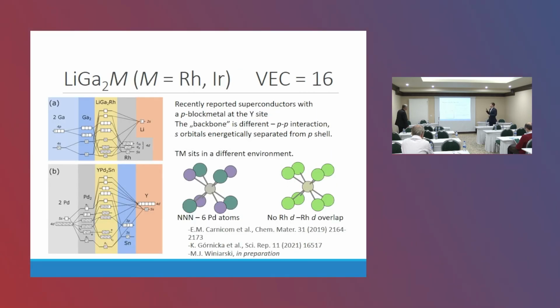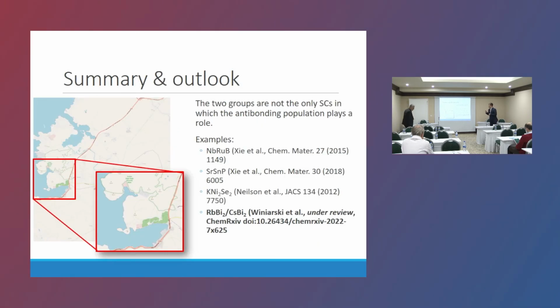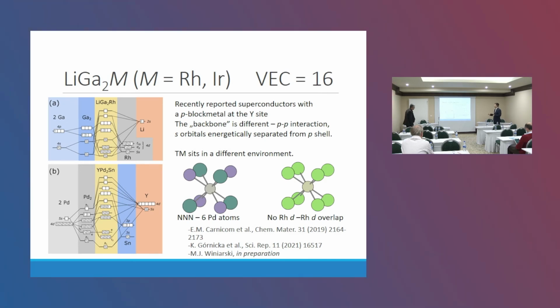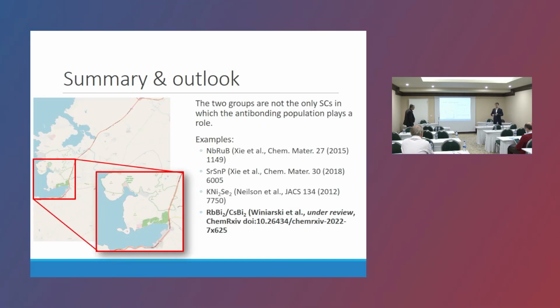And to summarize, I hope I convinced you that we were able to map our tiny little neighborhood, but that's not the only superconducting materials and superconducting families in which the anti-bonding population plays a role. We have reported by our colleague Winiarski, by Jamie Nielsen, for example, and our recent paper, rubidium bismuth 2, in which we find that the relativistic chemistry effects stabilize the structure, prevent the distortion, but then it leaves the instability, leaves a footprint in the electron conduction.